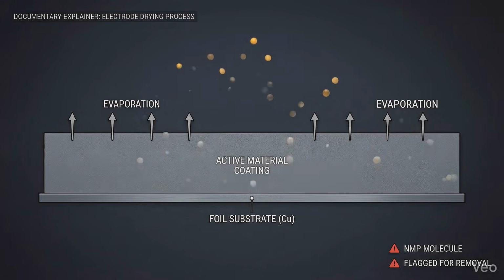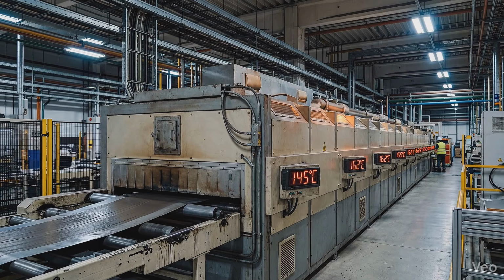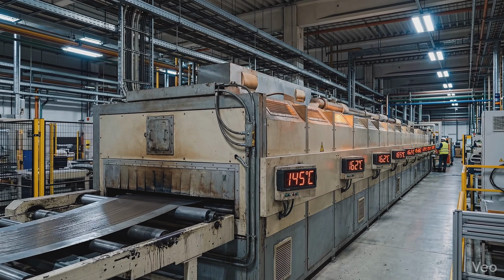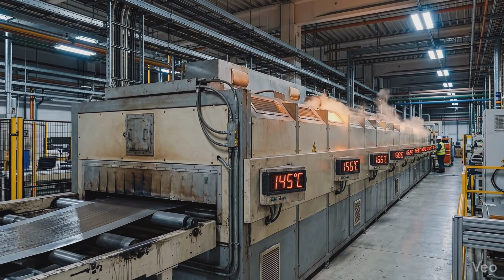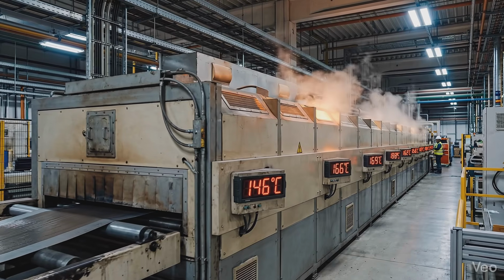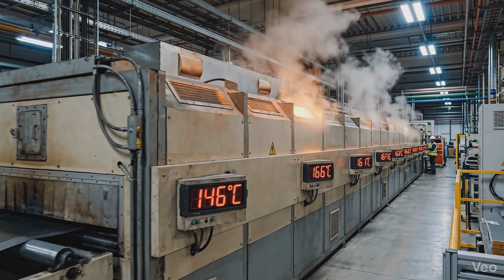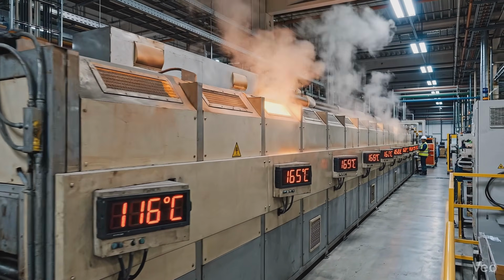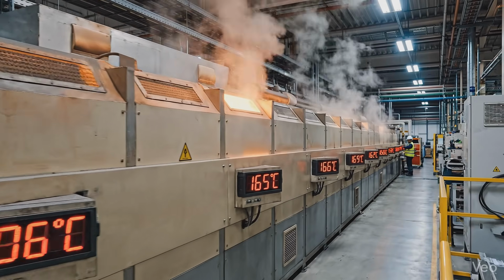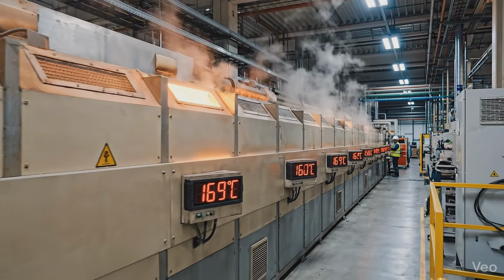NMP keeps the coating spreadable and uniform, but it has to be removed completely before the electrode can be used in a cell. Evaporating NMP requires sustained, carefully controlled heat, typically between 120 and 180 degrees Celsius, applied across enormous conveyor-fed ovens that can stretch the length of a football field.